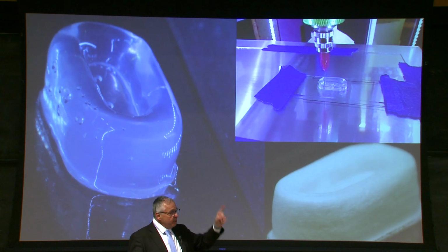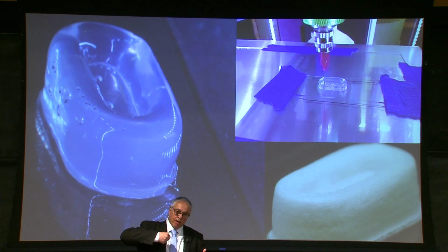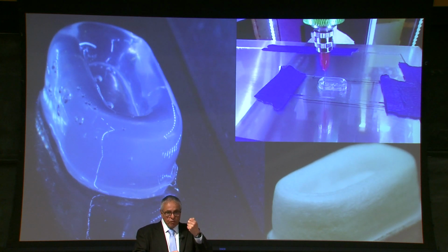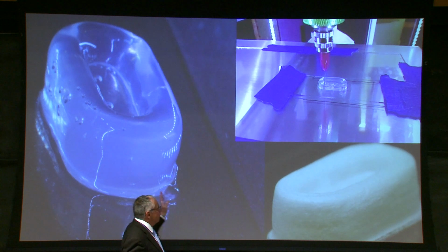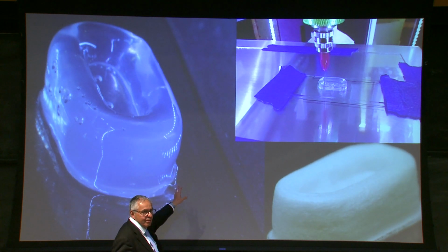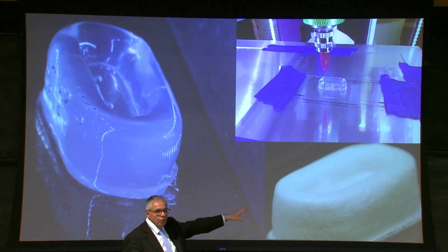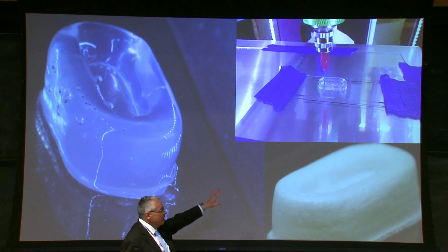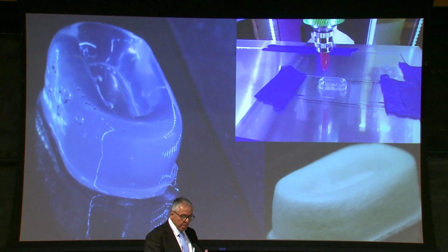And we actually took an STL file of a butterscotch candy, and we printed from water at room temperature a 3D structure. The reason we've been able to do it is because when we apply pressure on the plunger, despite the fact that the initial viscosity is very high, because of the shear force in the needle, the viscosity dropped dramatically. So tiny droplets were going out, but once they hit the stage, it solidifies. That's beautiful, except this is like Jell-O, okay? Don't touch it. But once you freeze it and lyophilize it, it actually keeps the structure, which is beautiful.